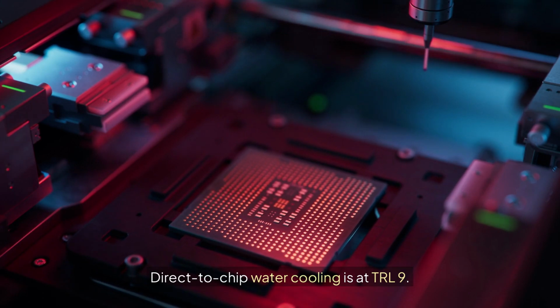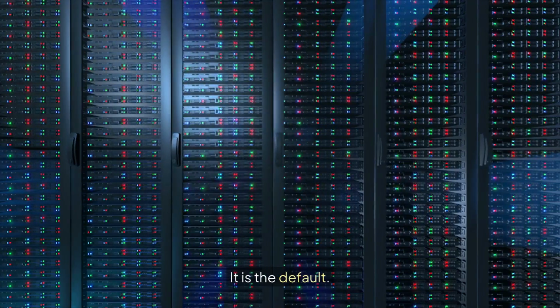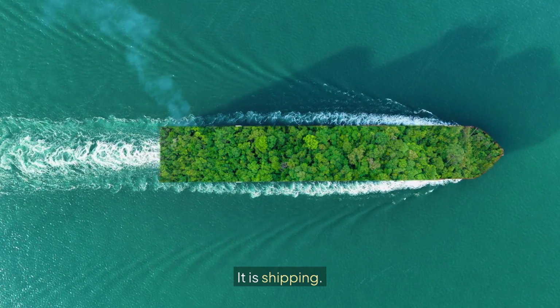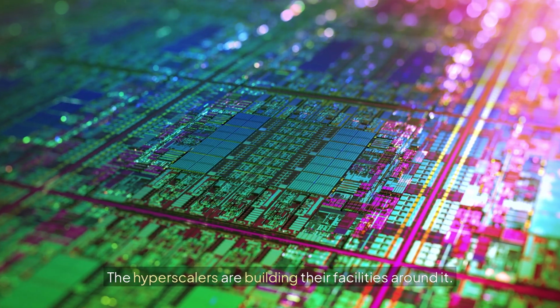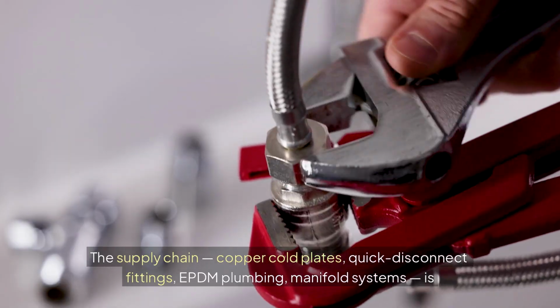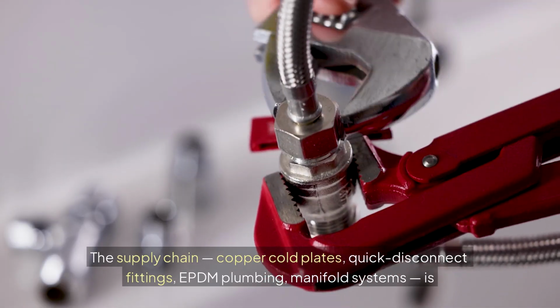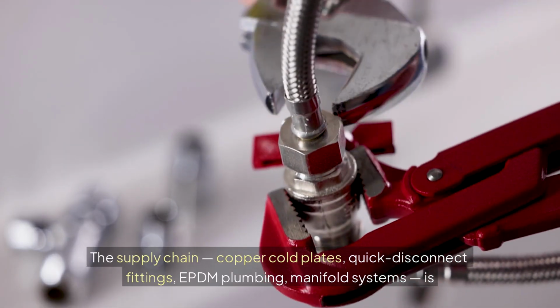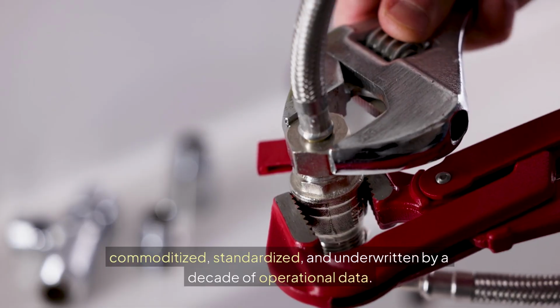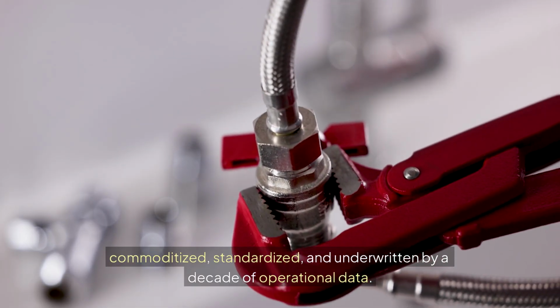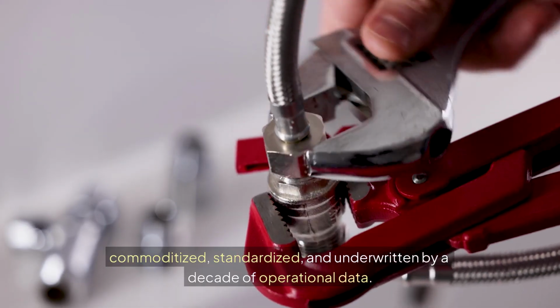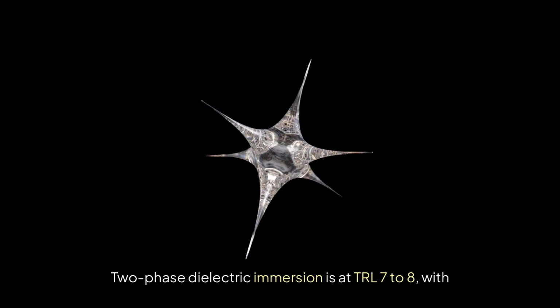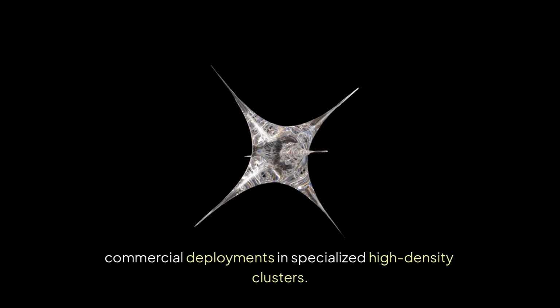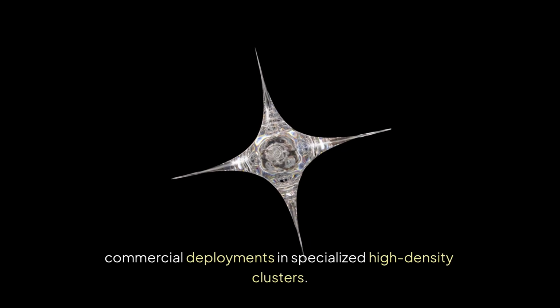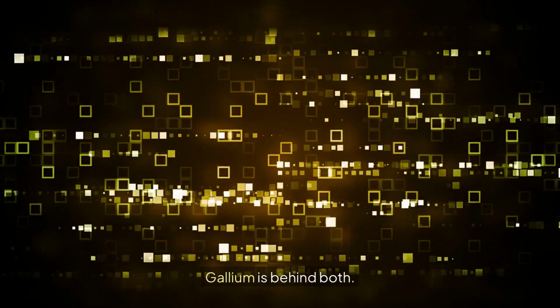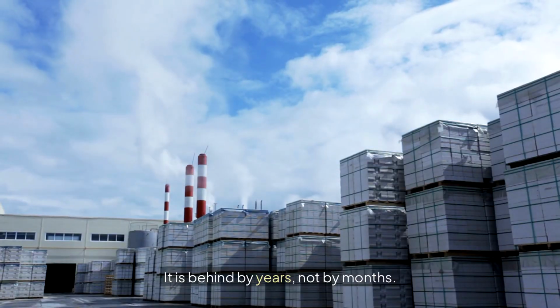Direct-to-chip water cooling is at TRL 9. It is the default. It is shipping. The hyperscalers are building their facilities around it. The supply chain, copper cold plates, quick disconnect fittings, EPDM plumbing, manifold systems, is commoditized, standardized, and underwritten by a decade of operational data. Two-phase dielectric immersion is at TRL 7 to 8, with commercial deployments in specialized high-density clusters. Gallium is behind both. It is behind by years, not by months.